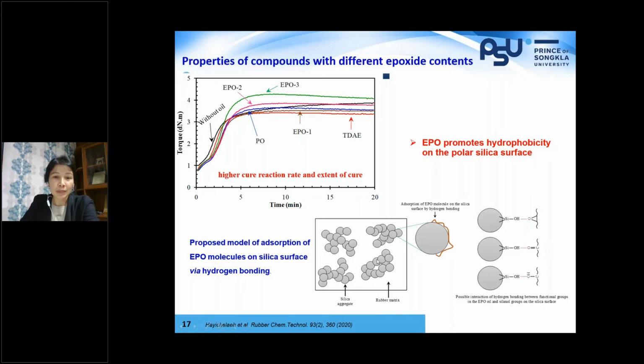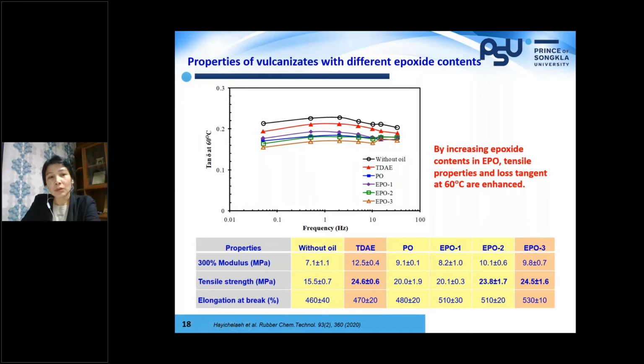So in the presence of oil, the absorption of these oil molecules can introduce hydrophobicity on the silica surface. So we can see that we have better cure properties in the presence of this kind of oil. In terms of dynamic property, if we look at tan delta at 60 degrees, which has been used as an indicator for tire rolling resistance, compared with the one without oil and TDAE, by using this modified oil or even the palm oil, the original one, we see a reduction in tan delta, which means if we use this compound for tire tread, we expect to have a lower rolling resistance.